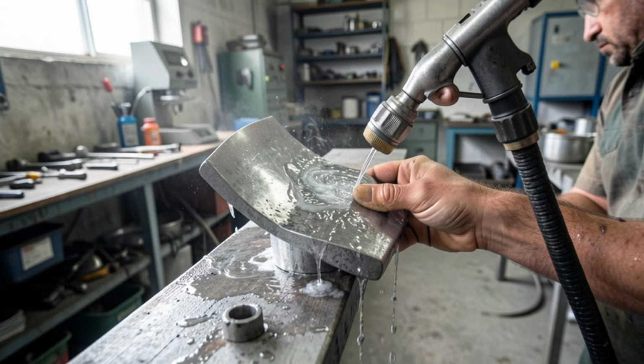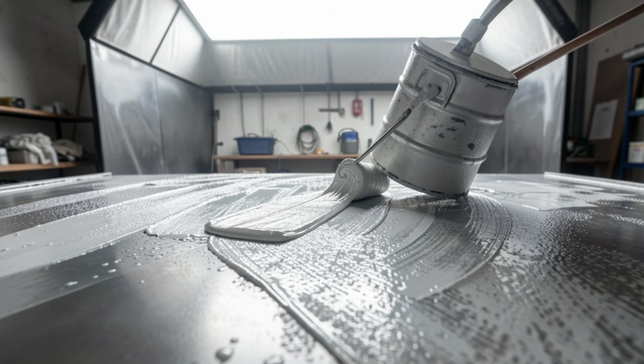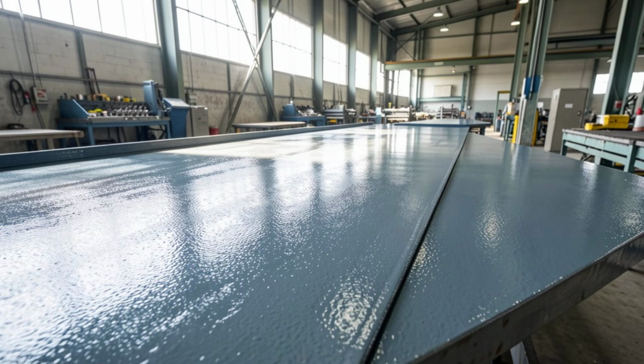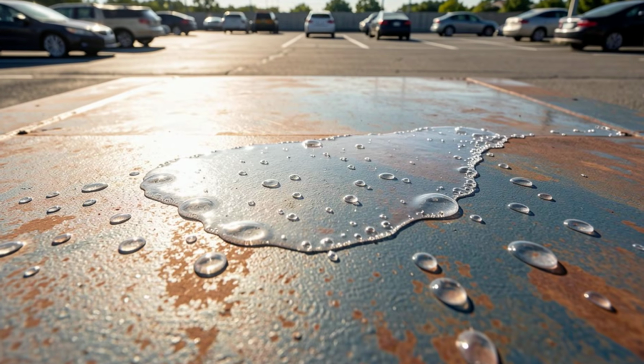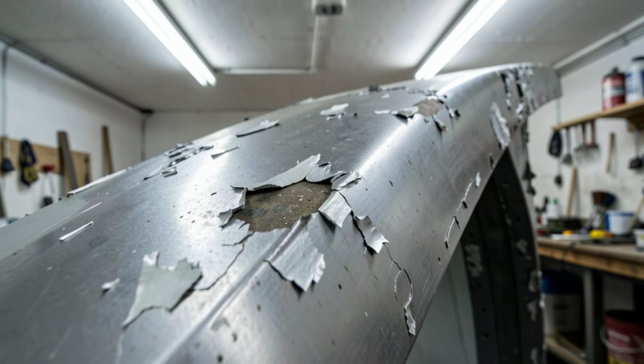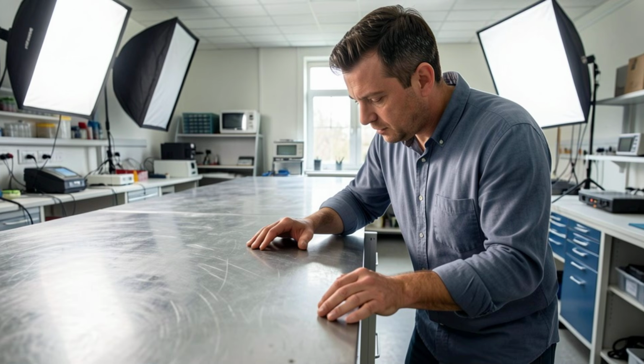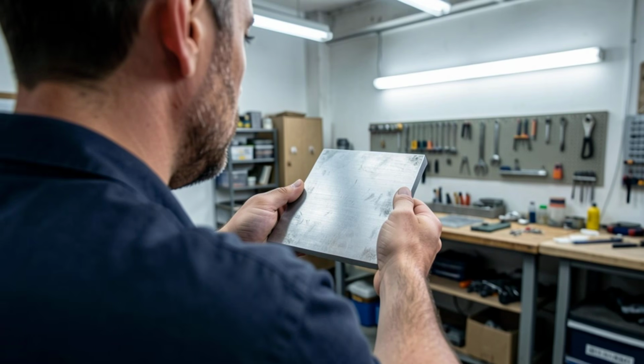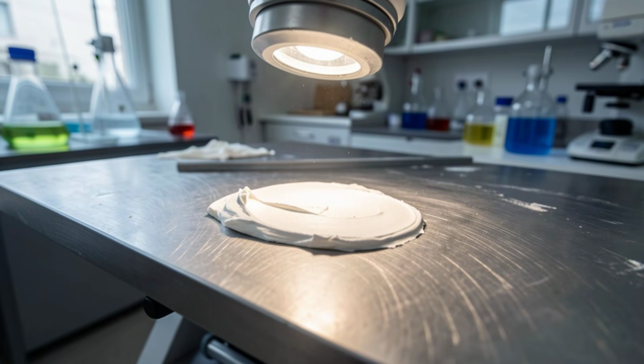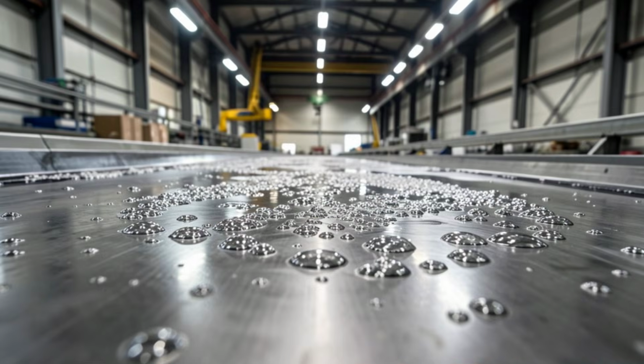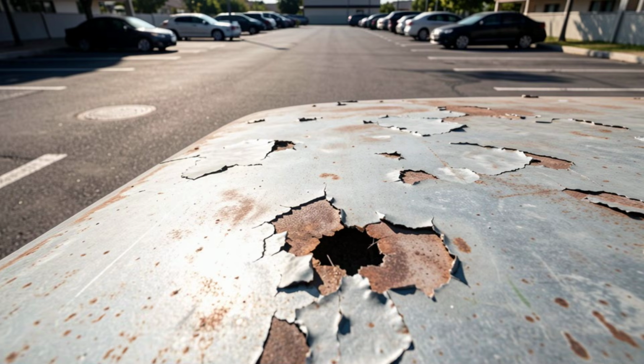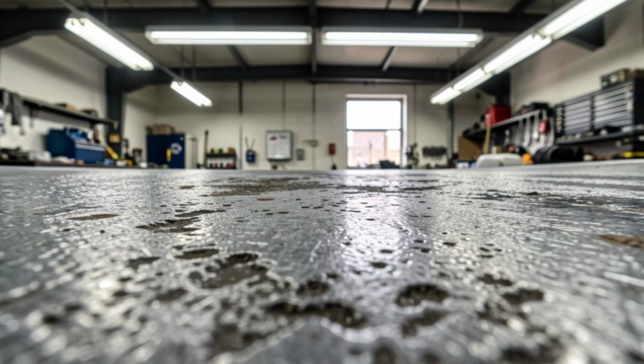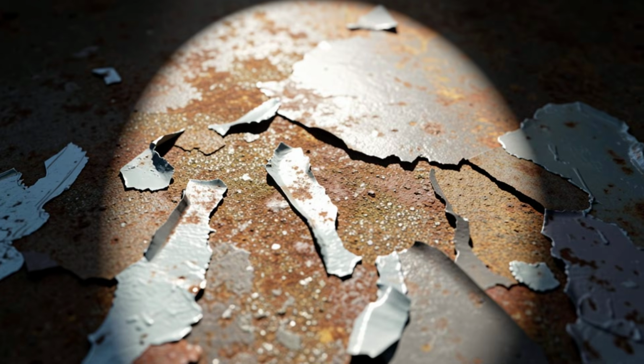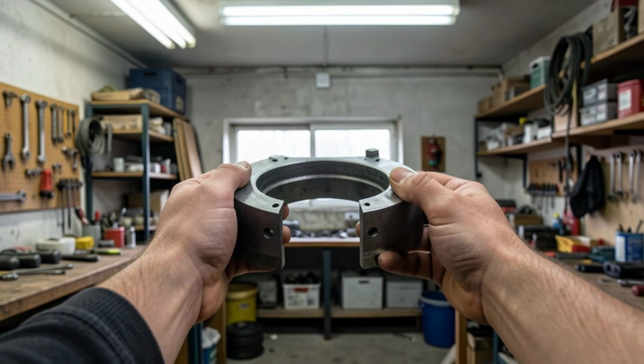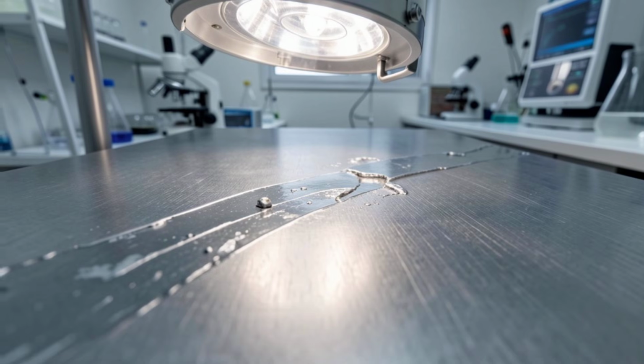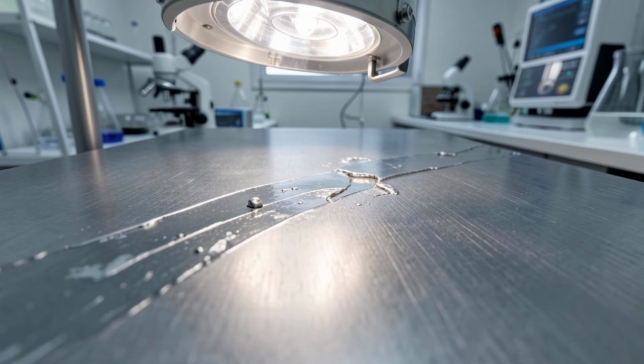Beyond the surface attack issue, many of these concentrated formulas leave a chemical residue layer on the metal after the product is rinsed away. That residue is thin, it is invisible, and it actively interferes with paint and primer adhesion at the molecular level. You prime over it, the primer looks perfect going on, you paint it, it looks great for a few weeks, and then the primer begins to lift and bubble and peel, because the bond between the paint film and the metal surface was compromised from the beginning by chemistry you could not see.